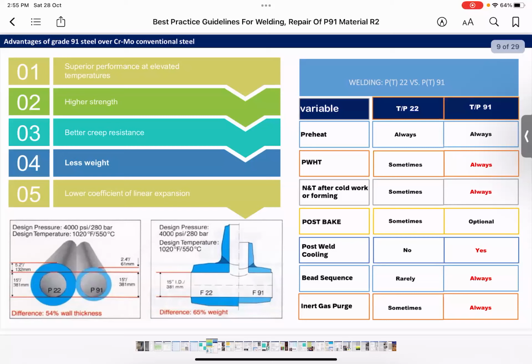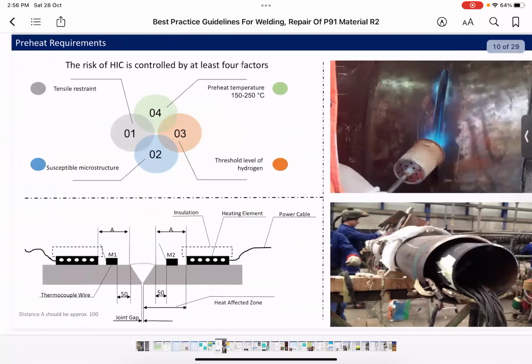For post-weld cooling, it is not required in P22, but it is very important for P91 in order to achieve the martensitic structure in P91. The bead sequence is always required. We have to follow the bead sequence from the bevel side to the center of the bevel, and inert gas purging is always required, not only for the root pass but also the hot pass as well, and we'll speak about it in the upcoming slides.